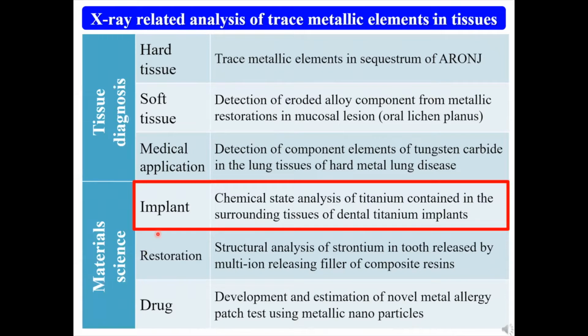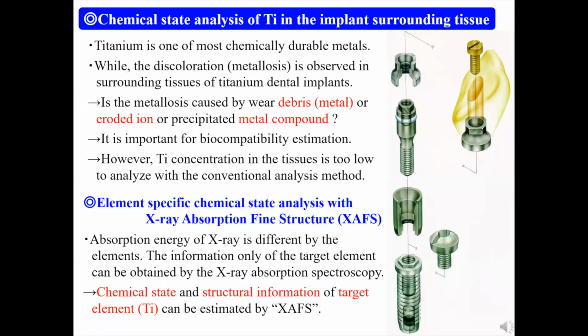The first topic is the chemical state analysis of titanium in the surrounding mucosal tissues of dental implants. As you know, titanium is one of the most chemically durable metals. However, discoloration, metallosis, is observed in surrounding tissues of titanium dental implants. It might be caused by micro debris from the implant screwing, but erosion of the implant titanium is suspected. It is important for the safety and biocompatibility of dental titanium implants. How the titanium is contained in the tissues should be identified to estimate the biocompatibility.